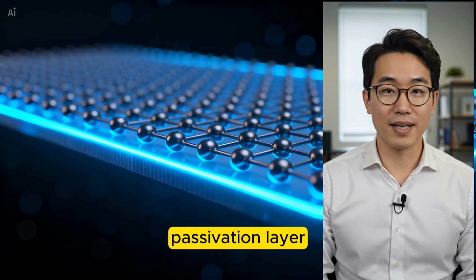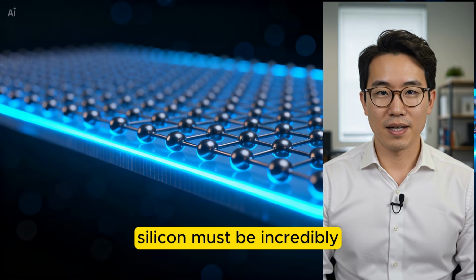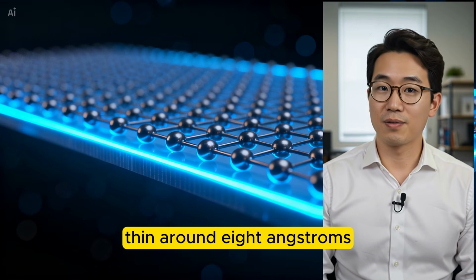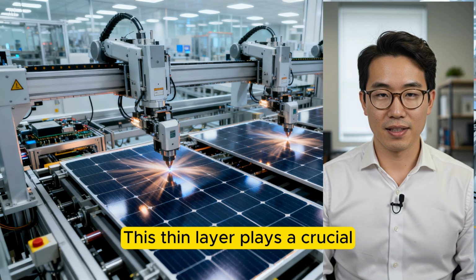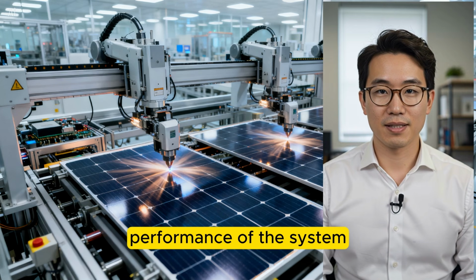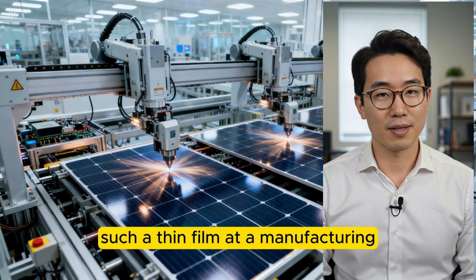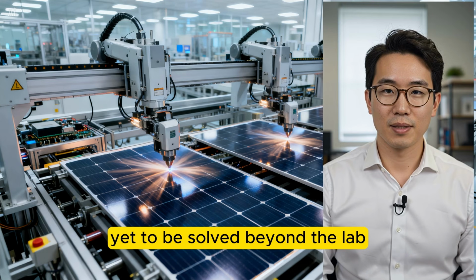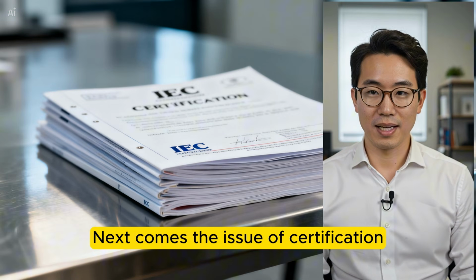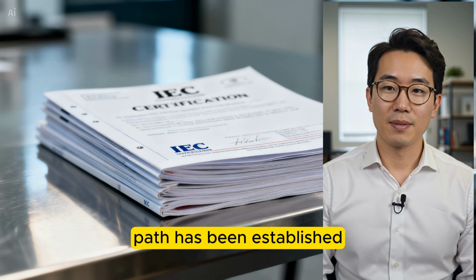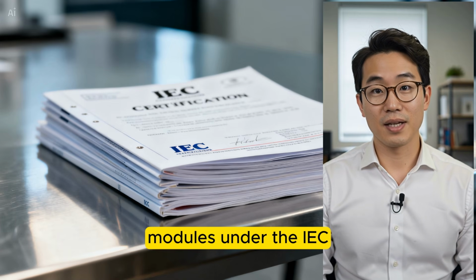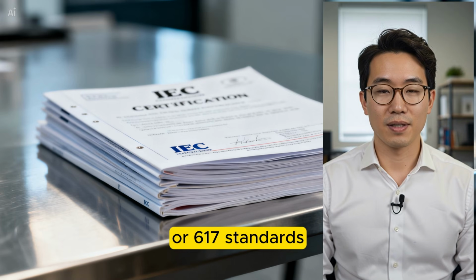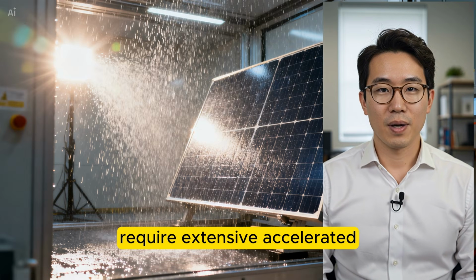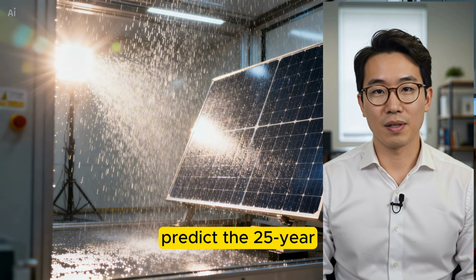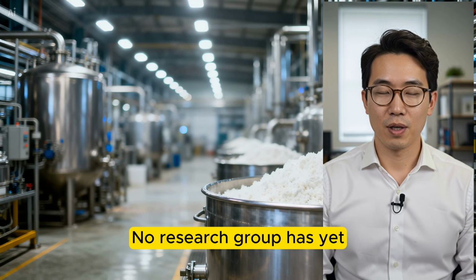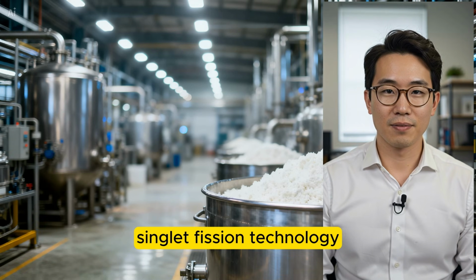MIT's research demonstrated that the passivation layer between the organic material and silicon must be incredibly thin, around 8 angstroms, which is approximately 4 atoms in thickness. This thin layer plays a crucial role in the overall performance of the system, but controlling such a thin film at a manufacturing scale remains a precision challenge that is yet to be solved beyond the lab. Next comes the issue of certification. Currently, no certification path has been established for singlet fission-enhanced modules under the IEC 61215 or 61730 standards. These standards require extensive accelerated lifetime testing to predict the 25-year outdoor durability of solar panels. No research group has yet conducted these tests for singlet fission technology.